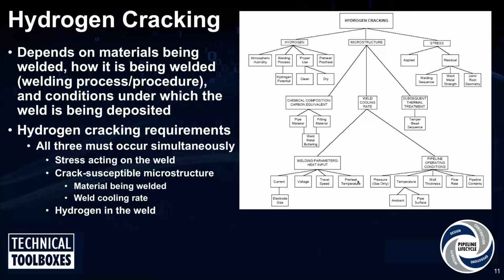All right, so the other aspect again is hydrogen cracking. Now, again, there's a lot of factors that affect hydrogen cracking, but like burn through risk, there are three primary factors. And those three factors are hydrogen in the weld, a crack susceptible microstructure, and some sort of tensile stress. Now, tensile stress, yes, there are external applied stresses that you have to be worried about, settlement stresses. But one of the big drivers for the tensile stress of in-service welds is just welding residual stress. And you have to accept the fact that you'll have some level of stress. So what most companies do to try to minimize the risk of hydrogen cracking is then address the other two factors, which is hydrogen content and microstructure.